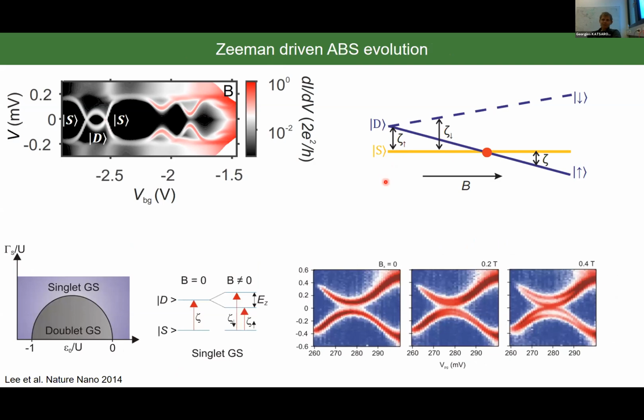This is similar to what Eduardo reported for Zeeman-driven Andreev bound state evolution. You see his graph at zero magnetic field, and while he cranks up the magnetic field, you can see the beautiful splitting. And as you see, if you have a singlet ground state, you will eventually have a zero bias peak when the singlet and the doublet merge.